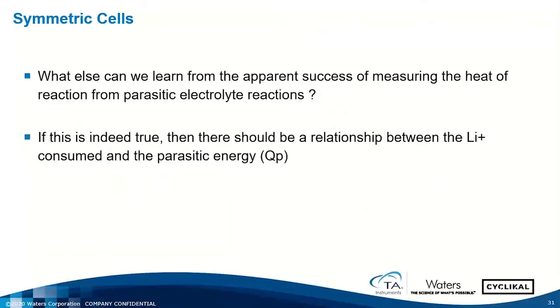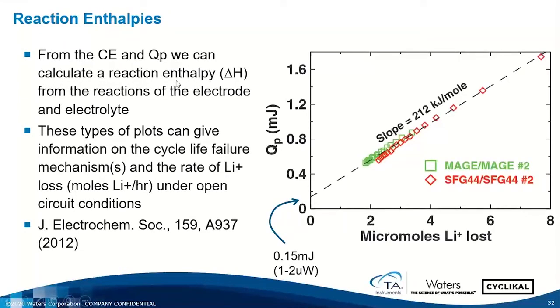All right, what else can we learn from this? If this is indeed true, then there should be a relationship between consumed and parasitic energy. So from the Coulombic efficiency and this thermal energy, we can calculate what I call a composite reaction enthalpy, a sum or a weighted sum, perhaps, of all the reactions of the electrode and the electrolytes. So what I'm doing here is plotting the thermal energy versus the number of moles of lithium lost, which we can back out from the Coulombic efficiency measurements.